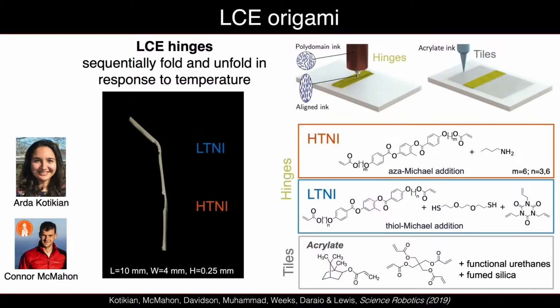So the next thing we did was we started thinking about origami. You could do this, of course, with the same material and different print speeds as I just showed, but at this time we hadn't done some of that fundamental work. And so the way we introduced origami hinge-like architectures was to do bilayers. So now we developed two different types of liquid crystal elastomer materials. One we call high TNI, so it shape morphs around 95 degrees C, and another one that shape morphs at a much lower temperature, a low TNI value.